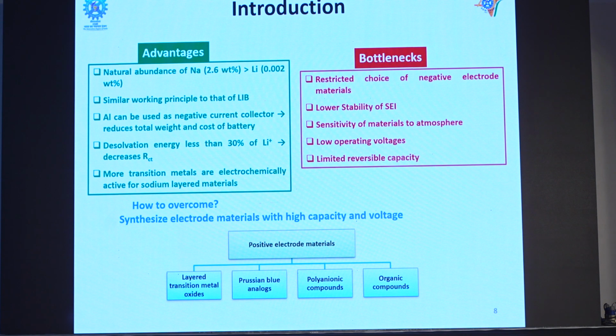And crystal structure is very important when it comes to lithium intercalation, and lithium intercalation is the fundamental behind the battery. That's why these materials should be stored in a glove box or in a dry room where the humidity is highly controlled. Another issue is limited reversible capacity. The first generation sodium ion positive electrode material was polyanionic compounds. The polyanionic compound sodium vanadium phosphate has a very low capacity, about 117 milliampere hours per gram. 117 is not enough when we compare it with a lithium ion battery.